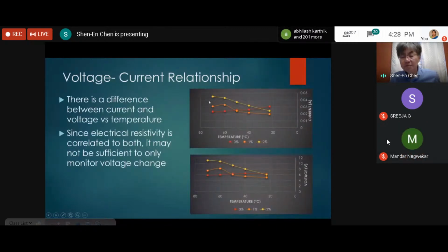And then using temperature change versus the current change and the voltage change, you notice that there's actually a drop in both voltage and current measurements. Okay, so this shows that when you have 0%, when you have no steel fibers, you actually see an upward trend. But when you add the steel fibers, you see a downward trend. And the 2% material performs better than the 1% with the filler materials.